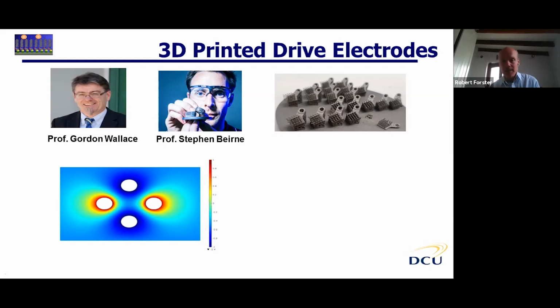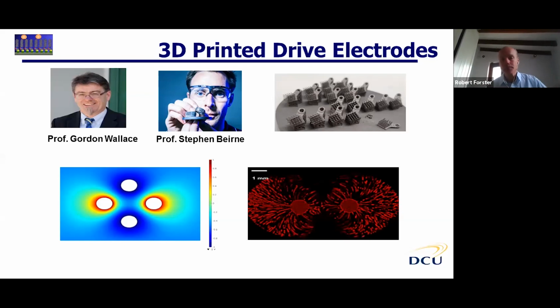One of the challenges in this space is the Gouy-Chapman-Stern model, very successful at explaining double layer structure of conventional electrodes. In these experiments, we're working at a very dilute electrolyte concentration, and you rapidly run into one of the fundamental underlying assumptions of GCS theory, namely that the charges are point charges. That allows you to pack as many ions as you want onto the electrode surface. Of course, in physical reality that is not true, but the models use that assumption and cause some problems with the COMSOL model.